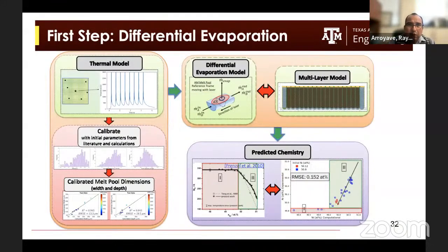So we have one first step in this direction, and actually one student that was a lab mate of Kubra for a few years, Dr. Milad Ranayefar, he just defended his thesis a couple of weeks ago. He developed a modeling framework where he was able to connect a thermal model that was developed initially by Air Force Research Lab, that was calibrated against experiments, to a model that predicted the differential evaporation of nickel in nickel titanium shape memory alloys. So we would basically predict how much nickel loss existed in a melt pool.